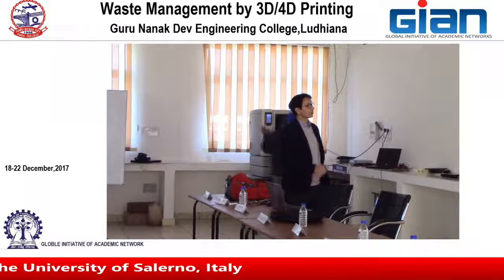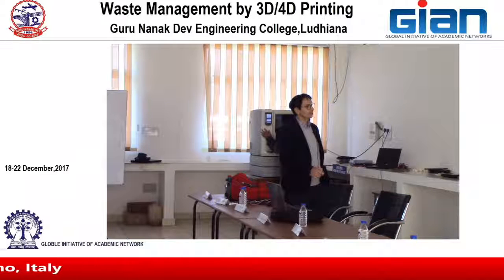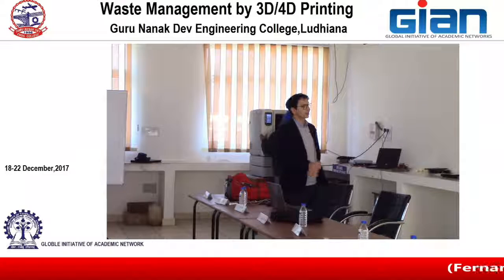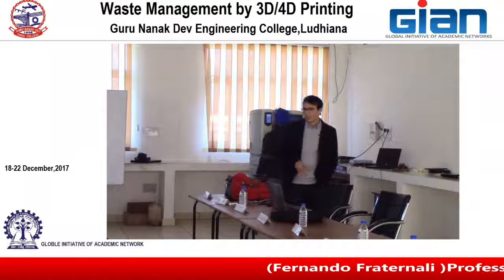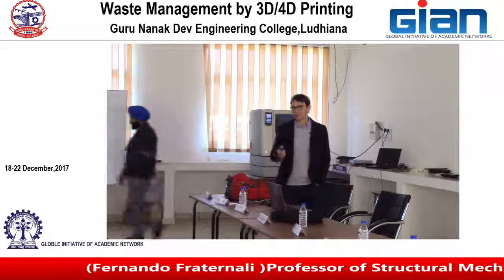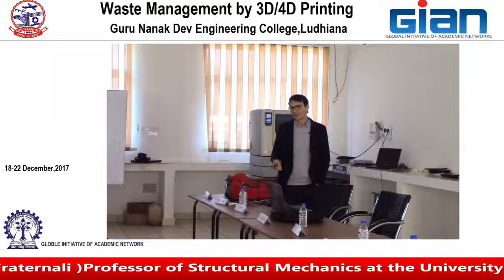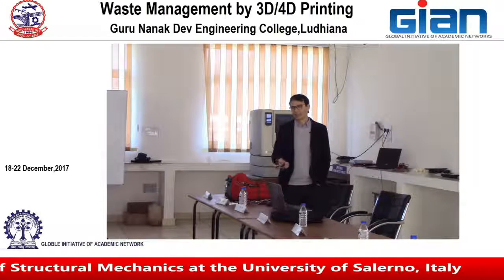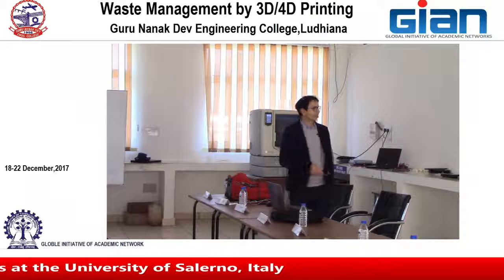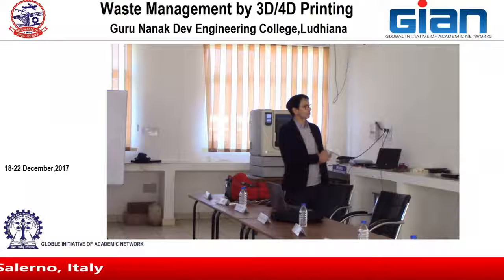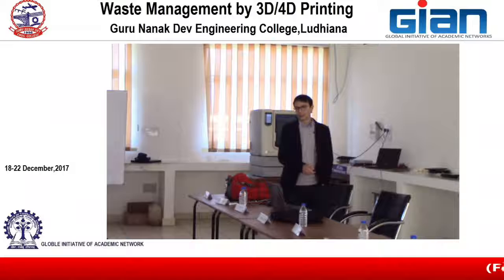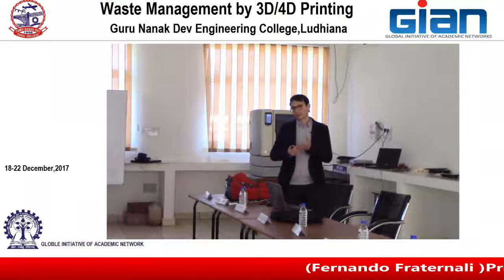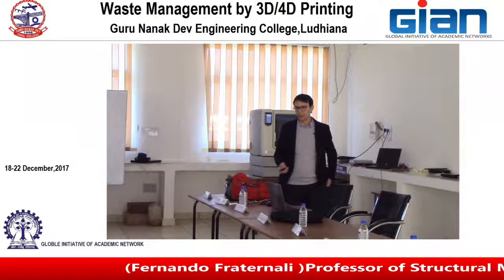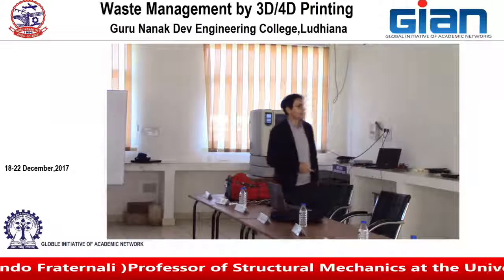And this is the response of the unreinforced concrete, which is dramatically brittle. I don't have a movie of the brittle specimen because actually it was very fast. But you can believe me that in this case, basically the load goes quickly to zero. The specimen breaks into two pieces, and the load goes to zero very fast.